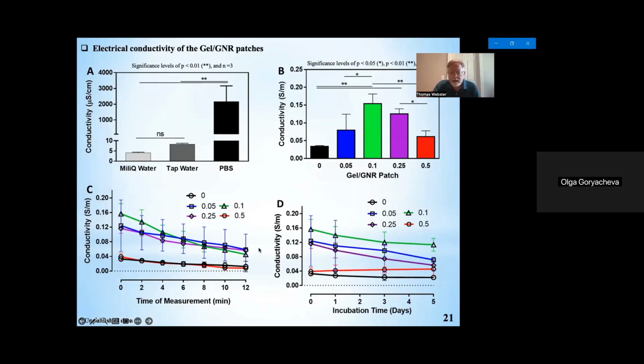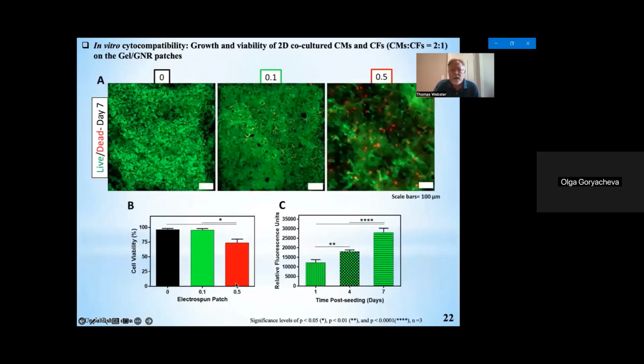And that conductivity maintains with time of culture in cell culture media. So we're pretty happy with all of those, but most importantly, the cytocompatibility results. These are cardiomyocytes that were cultured with cardiac fibroblasts, a co-culture system. They were seeded on a plain gelatin and then a gelatin with 0.1 weight percent graphene nanoribbons and 0.5 weight percent graphene nanoribbons. You can see that there are concentrations in which we start getting a slight reduction in the cardiomyocyte cardiac fibroblasts viability. So when going from 0.1 to 0.5, you can see in the live dead assay, we are seeing a couple more dead cells, which we don't want.